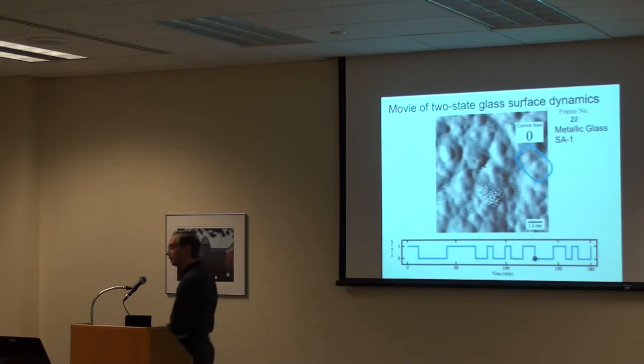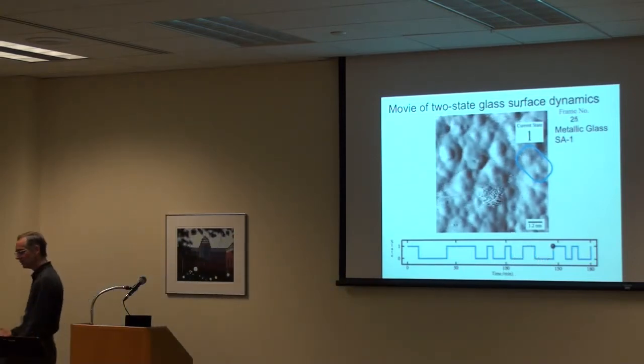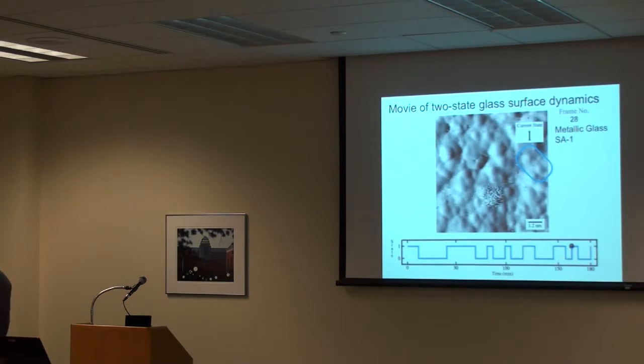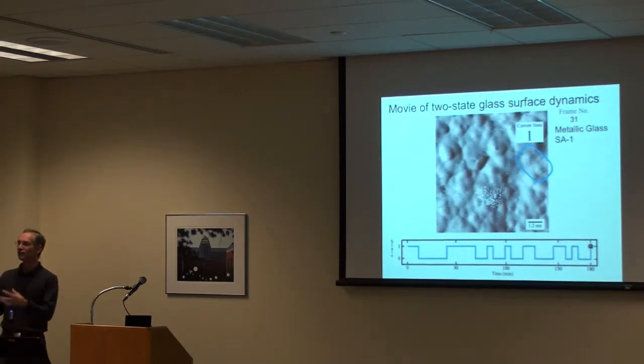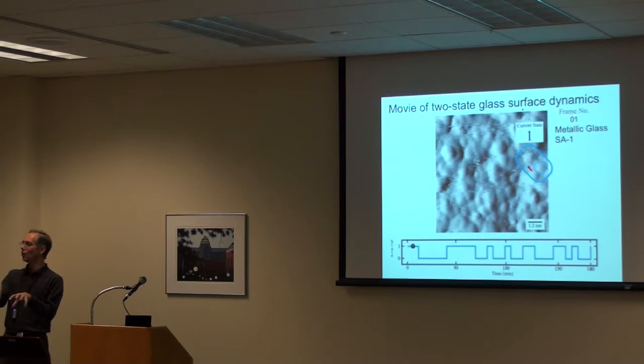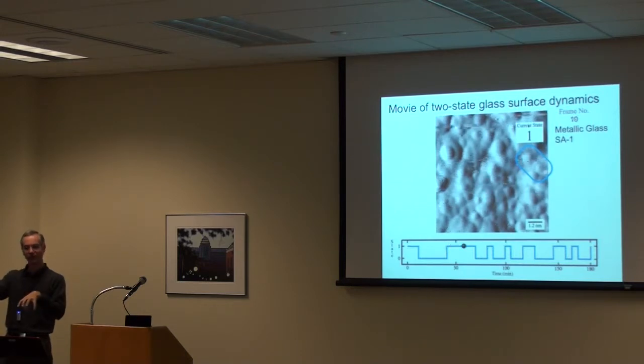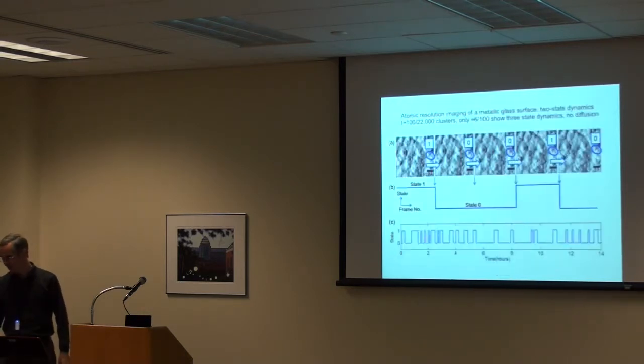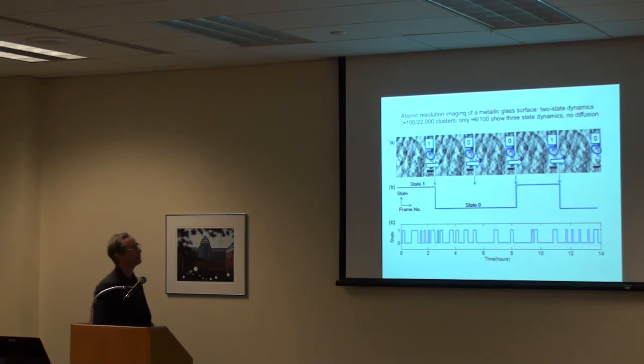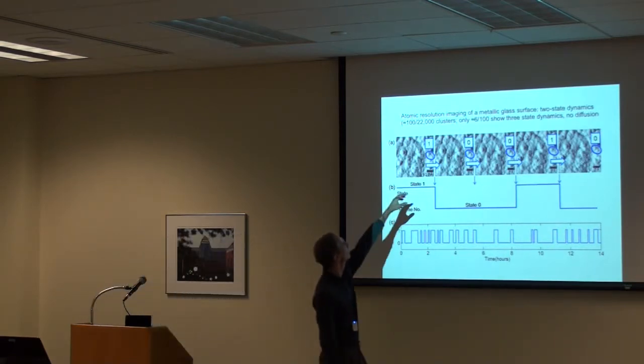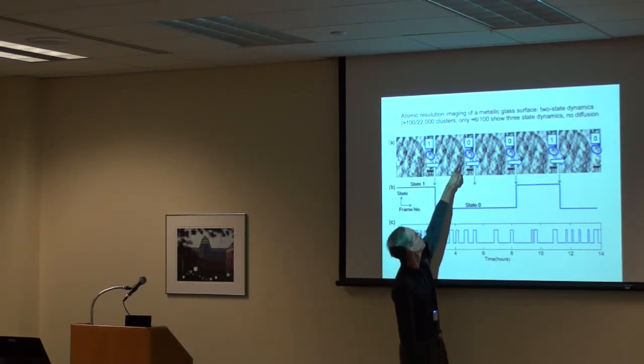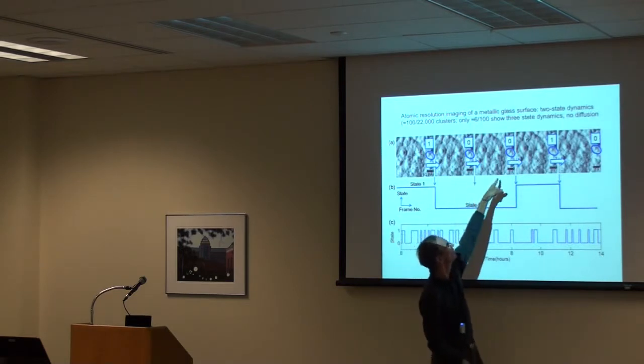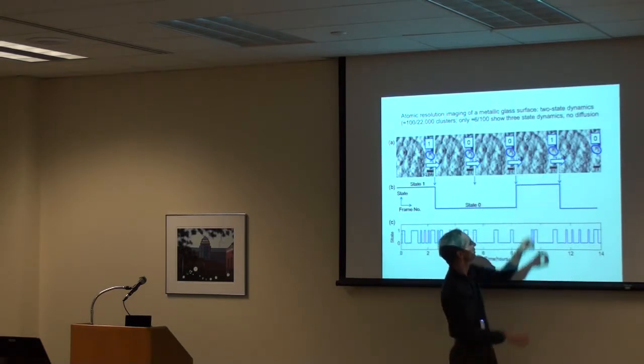And so indeed, the dynamics that we've seen, at least well over 90% of what we see on that surface, is just these clusters of a few atoms in diameter hopping back between two places on that surface, sometimes up and down, sometimes translating like what you see here back and forth horizontally. And so we can take movies like this. Here again, these two clusters are a little further apart. Here they've come closer together because one of them has hopped. They're still close together. It's hopped apart again and so forth.